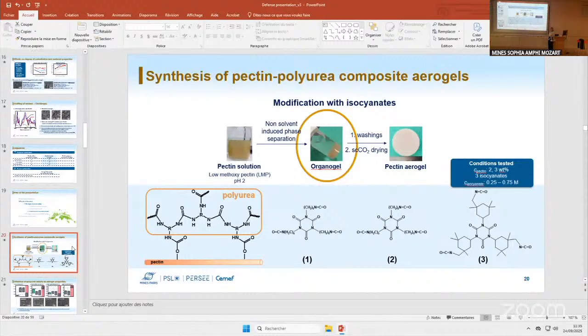But let's assume they are both there. If you don't have a lot of water, it means you have a large excess of isocyanate, probably. Which normally in polyurethane foams, if you have excess isocyanate, you make this isocyanurate. Yes, of course, in your precursors, you already have the structure. So in the NMR, you see the isocyanurate structure, but that's also because your precursors, like they're shown here, already have it. Do you know if you form extra isocyanurate structures, or have you not tried to see if this is possible to quantify? I don't know if we form more isocyanurate rings from our triisocyanates. I don't know if it's stable, if we could form.